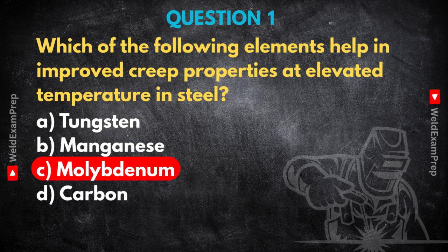Molybdenum, or moly as it's often called, really boosts steel's ability to resist this. How? Well, a couple of ways. First, it strengthens the steel's basic crystal structure, makes it harder for atoms to move around and deform. Second, and this is key at high temps, molybdenum forms very stable carbides, compounds of molybdenum and carbon. These little carbides don't break down easily, even when it's really hot. They act like tiny anchors inside the steel, stopping the grains from sliding past each other, which is what causes creep. Without molybdenum, the steel will just give way much sooner under that kind of stress.